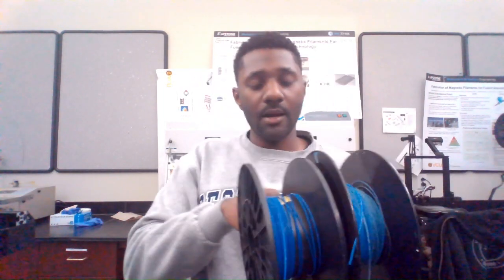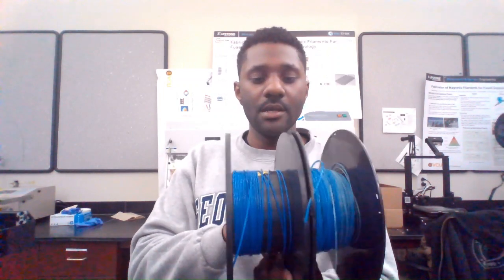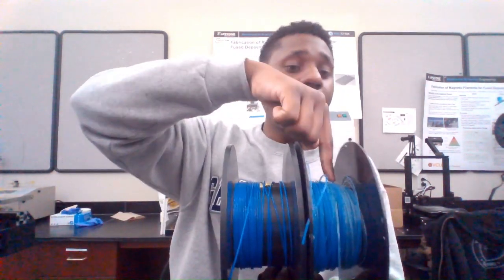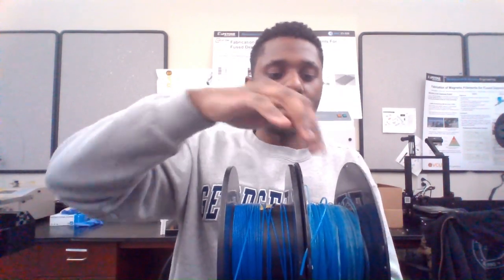And then we started to play around with the colorant mixing percentages, where we went from 5% mix all the way down to 2% mix in some instances, to see how well the diameter sensor would read, or how uniform our filament would come out when there's more blue colorant added versus less. We found that a stronger mix of blue colorant was more successful in extruding, and that between the 3 and 2% mix by weight range we were running into a lot of misreadings in the diameter sensor, or non-uniform diameter. Our diameter target is around 1.75 millimeters with 5% tolerance on either side. So that was what we were trying to achieve in our extruding testing.